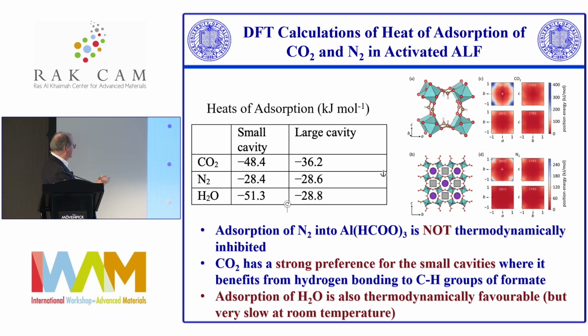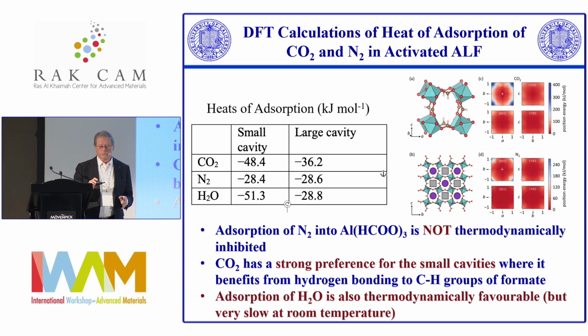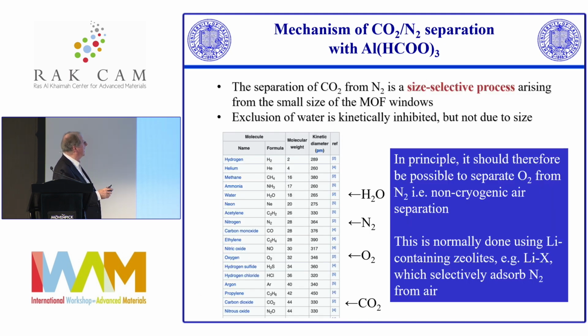So adsorption of nitrogen is not thermodynamically inhibited, but CO2 has a strong preference for the small cavities where it can enjoy the hydrogen bonding, and the adsorption of water is thermodynamically favorable, but also extremely slow at room temperature. So this obviously was a lot of food for thought as to what to do next.